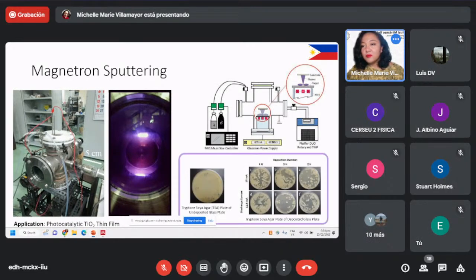We have actually produced a publication together with Dr. Luis using this study. We used this titanium dioxide to kill bacteria. So we tested a sample without titanium dioxide, and we tested a sample with titanium dioxide, and then we also exposed it to UV because TiO2 becomes bactericidal together with UV. And we have shown that if you deposit titanium dioxide onto your sample and then expose it to bacteria, we can see a lot of growth inhibition. Whereas if we do not deposit TiO2 onto the glass substrate, then the entire Petri dish is full of bacteria.